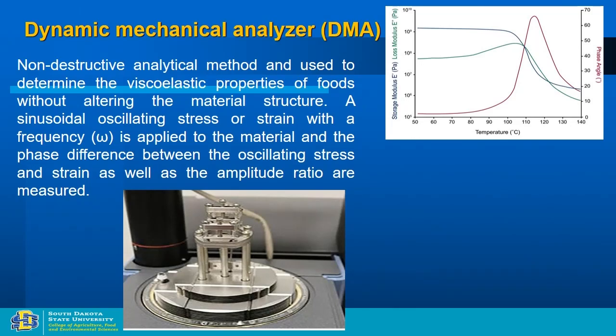So, what you see here is both the storage modulus, which is here in the blue color, and then the loss modulus is here. So, this is the crossover point. So, we can probably get similar kind of results to what I showed you in the paper, and it is a function of temperature here, and this is the phase angle. Phase angle is shown here as a function of the temperature.